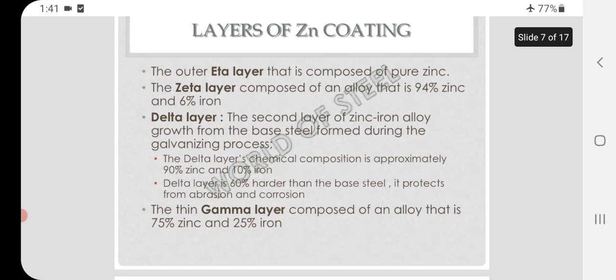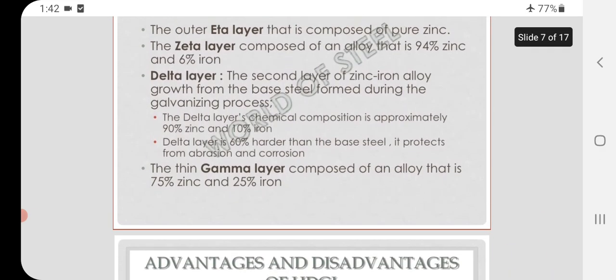The outer eta layer is composed of pure zinc. The zeta layer is composed of an alloy that is 94% zinc and 6% iron. Delta layer, the second layer of zinc iron alloy, grows from the base steel during the galvanizing process. The delta layer's chemical composition is approximately 90% zinc and 10% iron.